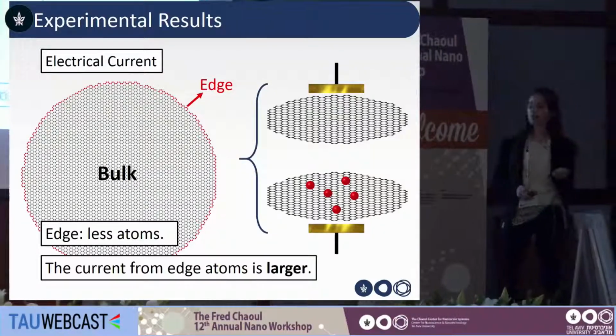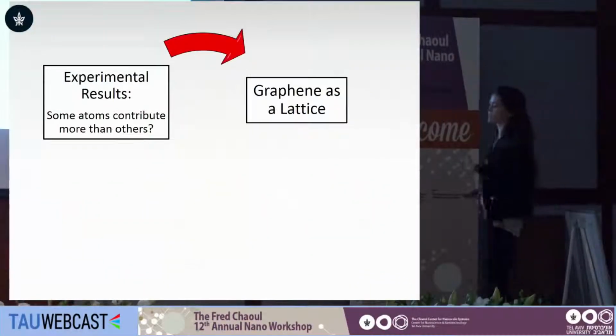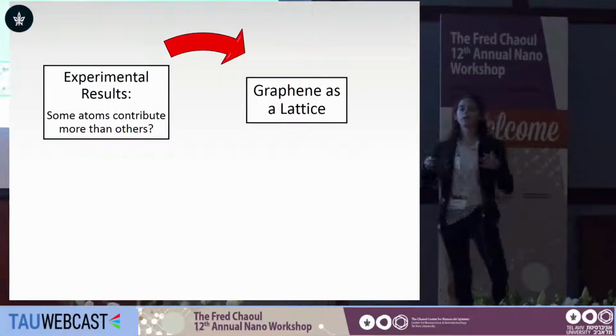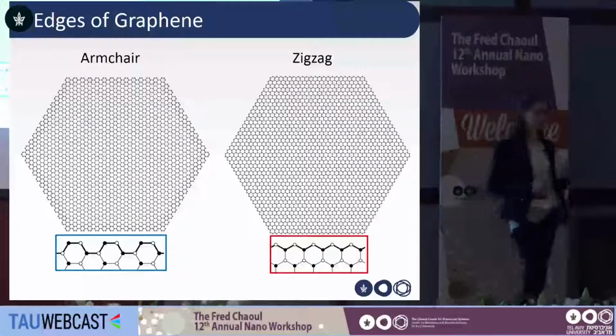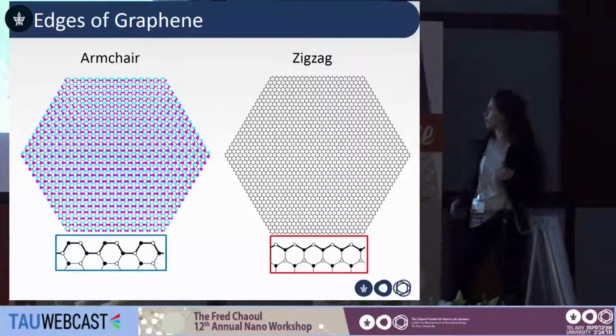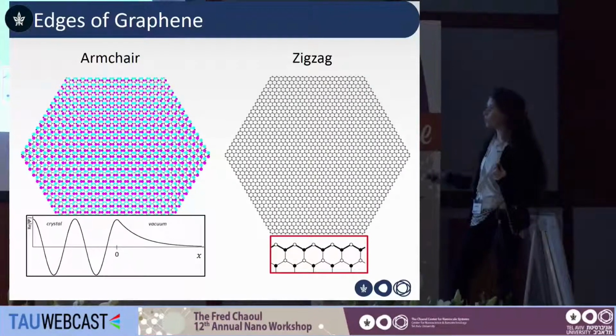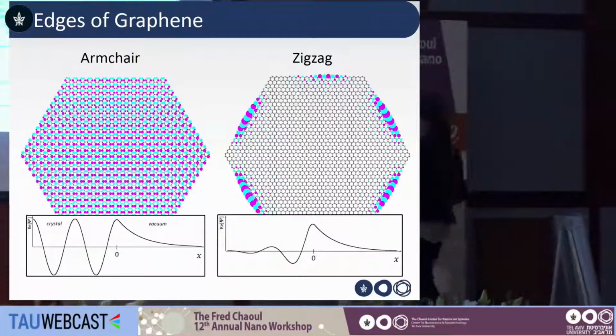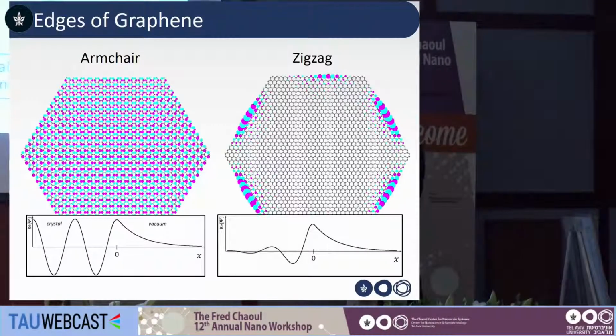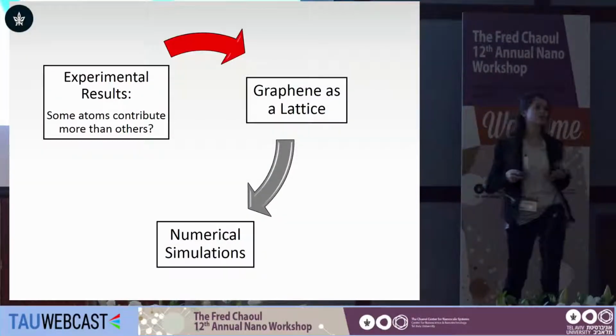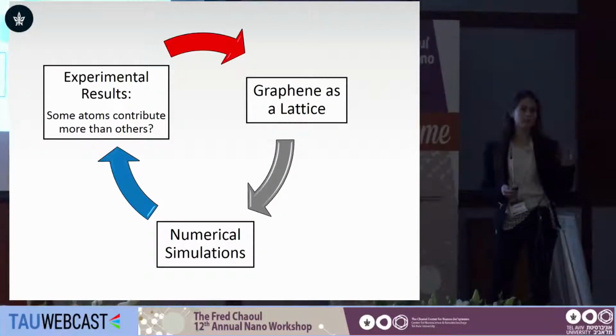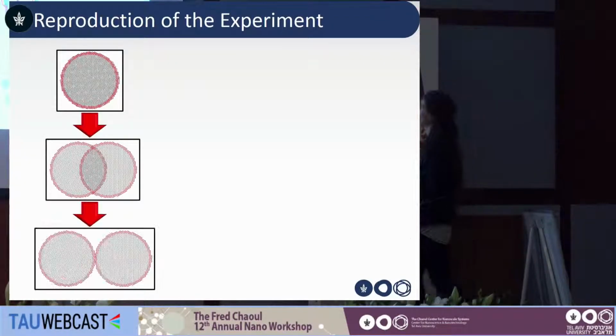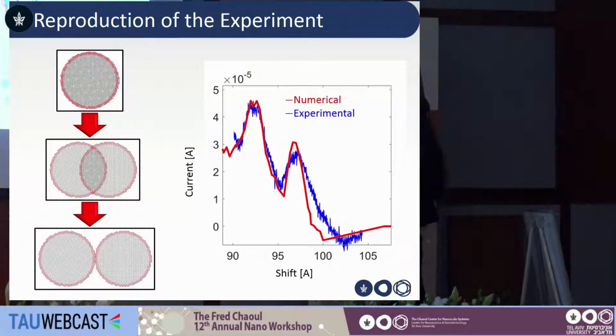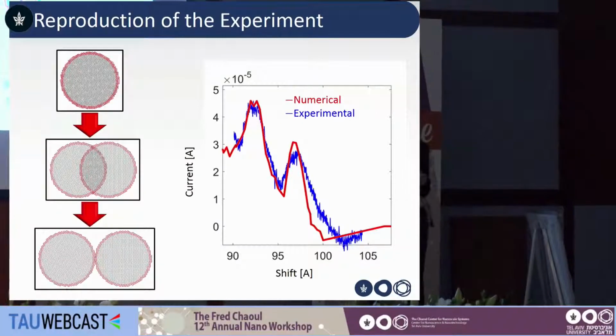To understand why, we treated graphene for what it truly is, which is a lattice, and we show that the way that you cut the lattice determines whether your wave function would be a bulk state, localized in the bulk, or an edge state, localized on the edge atoms. And based on this understanding, we derived numerical simulations that in turn enabled us to reproduce the experimental results. So for example, I can simulate two graphene flakes sliding relative to each other. I can plot the current as a function of the distance, and note how nicely the numerical results here in red reproduce the experimental behavior. Thank you.